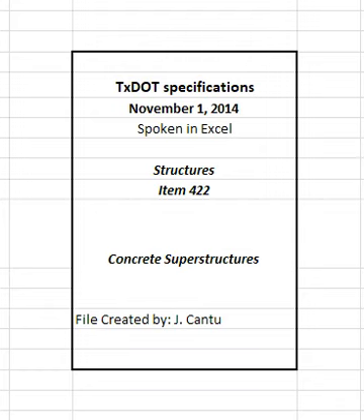Drill holes for anchor bolts to accommodate the bolt embedment required by the plans. Make holes for dowels at least 12 inches deep unless otherwise shown on the plans. Make the hole diameter at least twice the dowel or bolt diameter, but the hole need not exceed the dowel or bolt diameter plus 1.5 inches when using cementitious grout or epoxy mortar. Make the hole diameter 1/16 to 1/4 inches greater than the dowel or bolt diameter when using neat epoxy unless indicated otherwise by the epoxy manufacturer.